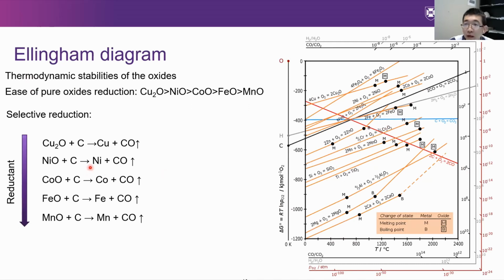So then from the nodules, we can do the selective reduction of the metals of interest. By controlling the reduction, we can control the reduction extent of these oxides, and probably we stop here to fully reduce the copper, nickel, and cobalt, and then partially reduce iron, and leave the manganese oxide not reduced in the manganese oxide rich slags.